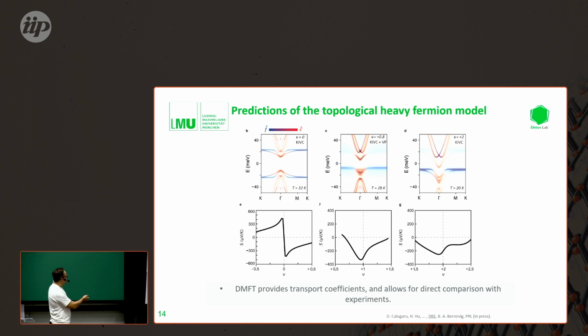And this ingredient, one can take into the calculations. And if one would take these spectra here, and try to do the DMFT calculations, and try to reproduce the Seebeck effect, one would get a very similar behavior. So one would get this normal sign-reversing symmetric Seebeck effect around the charge neutrality point, and one would get this very suppressed Seebeck effect on the heavy fermion side, on the side of the flat bands, as is seen here in these measurements.